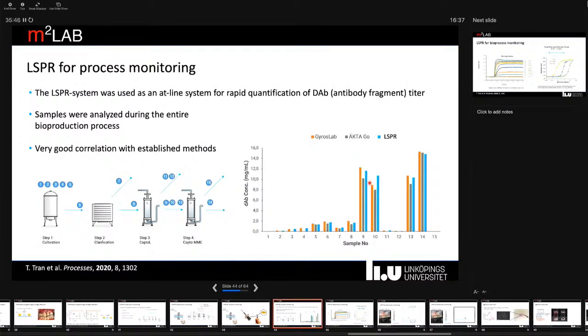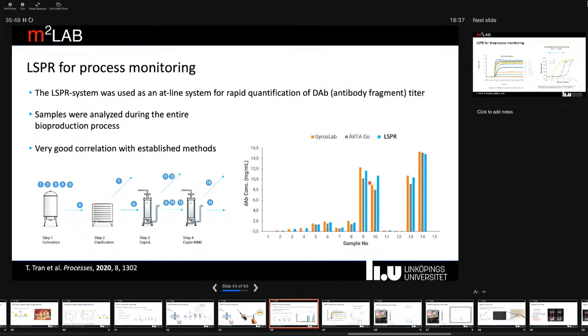And with this fairly simple device, we can outcompete essentially current techniques for at-line detection of, for example, titer, both with respect to sensitivity and dynamic range, but above all, the speed. Here we can get a result within minutes on the product titer throughout the entire bioprocess step, from the complex soup of biomolecules with very low titer concentrations in the upstream process throughout the purification and clarification steps. And very good correlation to these other methods that typically take hours to get the same results.